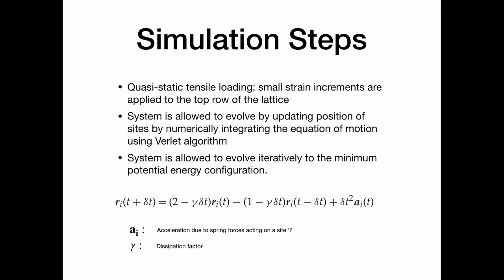Right. Now, the simulation steps, I will just run through. We apply quasi-static tensile loading, small strain increments at the top row. For boundary conditions, we restrict the bottom row to move only in the horizontal direction, so the vertical direction is restrained. Because of the deformation energy stored, you have forces coming onto particles, and those particles evolve. For each increment, we bring it to static equilibrium using a dissipation factor, and the Verlet algorithm is used for updating the particle positions. The acceleration of the particle is from the forces that it gets from its neighbors.